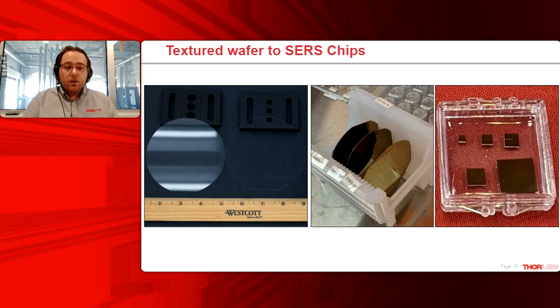Now, being an industry, we like to do things to scale so we can meet that availability requirement of SERS substrates. In this case, we use 4-inch quartz wafers. We'll take that wafer and we'll texture it. Then we coat it in some gold, and then we can dice them into individual chips for sale. And this is really where the characterization begins, because we need to ensure that the manufacturing process is consistent and uniform across the entire wafer and from batch to batch, from wafer to wafer.